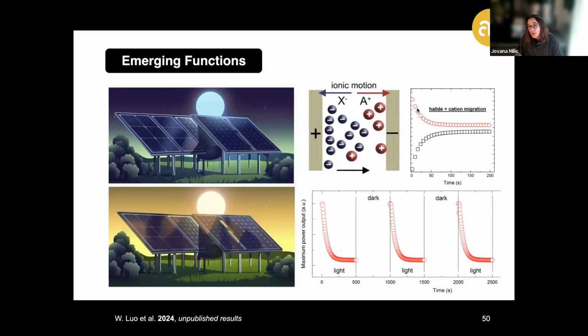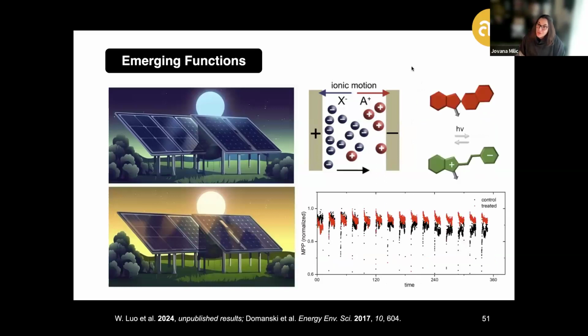However, this still involves a certain level of permanent degradation associated with ion migration, posing the question of whether we could control this process by enabling beneficial reversible motions of the ions while suppressing permanent, undesirable degradations. We explored this by relying on a number of photochromic systems, one illustrated here schematically, showing this is possible to achieve even in the solid state, mimicking the performance of solar cells with their changes through day-night cycles. This opens perspectives to tailor these stimuli-responsive systems more effectively in adaptive solar cell architectures.